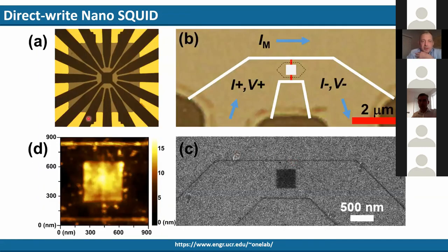And this zooms in on that. So this shows the center of the chip again. And in here you can see the insulating lines that were placed in to structure the device. The square represents the pickup area of the squid. And the red represents the nanojunction that are placed in. Figure C is interesting because that's a helium ion image that was taken right after we wrote a device inside a YBCO. And in a helium ion image the insulating regions actually look dark and you pick up the contrast. Here you have an AFM that shows the structure. And what you see with the AFM is the material is actually bulging where we irradiate it. So what happens is the helium goes down into the substrate and then kind of mechanically raises it up a little bit.